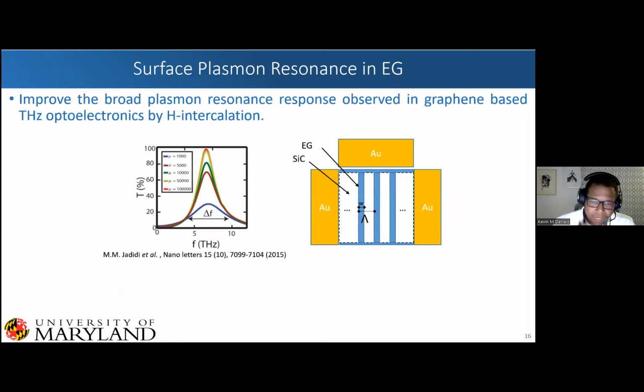And so this is a graph that was put together by a colleague, Mehdi Jadidi, where he was able to plot this out. Basically, this is plasmon resonance as a function of carrier mobility. So when they were using as-grown graphene, you notice the mobility was around 1,000, so you're getting pretty wide resonances. But as you increase the mobility going up to the theoretical 100,000, you get much, much narrower plasmon resonances. So the idea was, okay, well, we have this material with 4 times better carrier mobility, approaching 5,000, we see the same effect. And so we have our structure here.